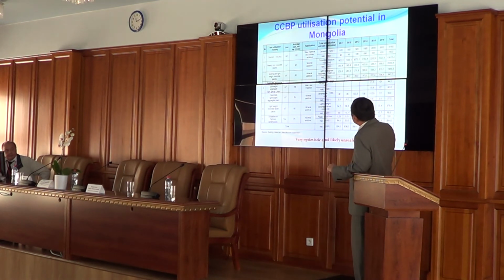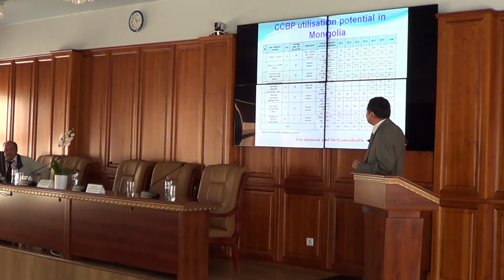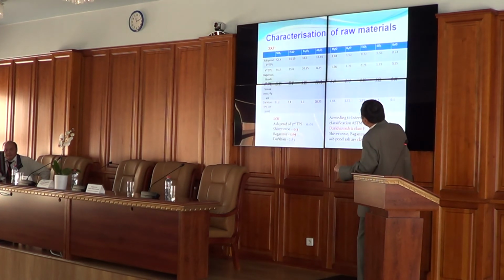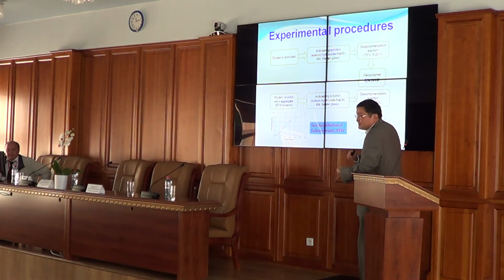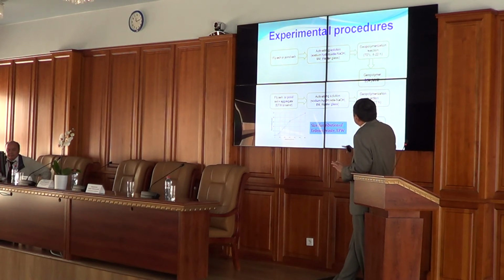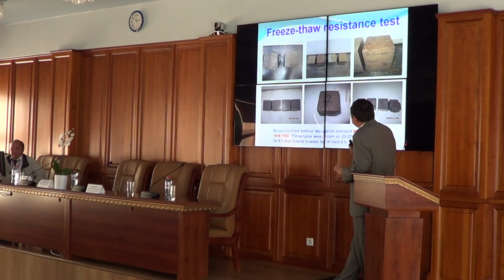Reduction, conversion and utilization are today's initiative in Mongolia. We have characterized our fly ashes and bottom ashes. Also, our experimental procedure: fly ash or bottom ash activated with a solution of water glass and sodium hydroxide to make a geopolymer. What have we got?